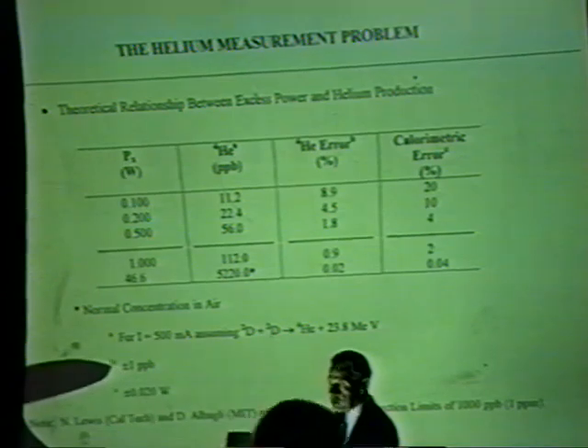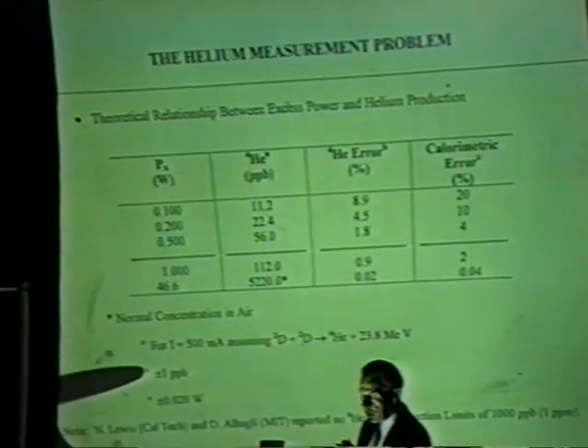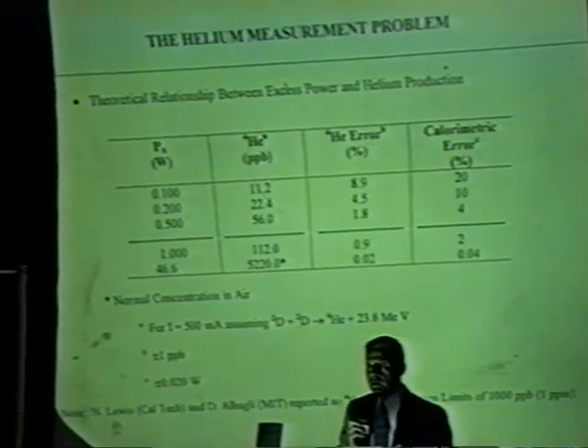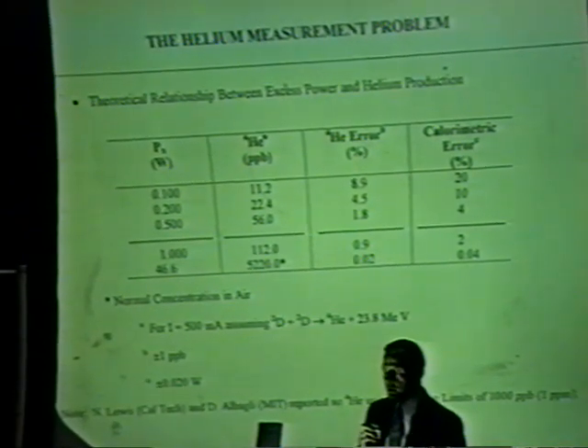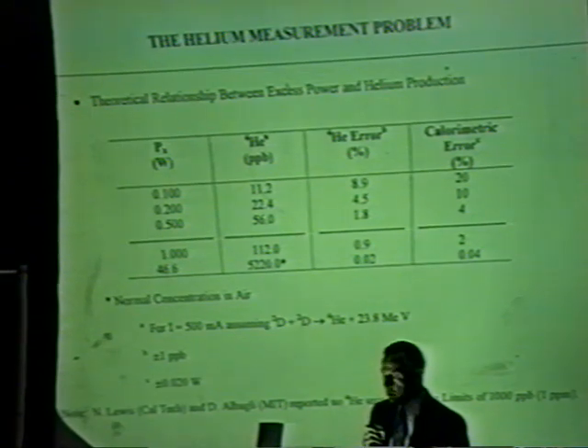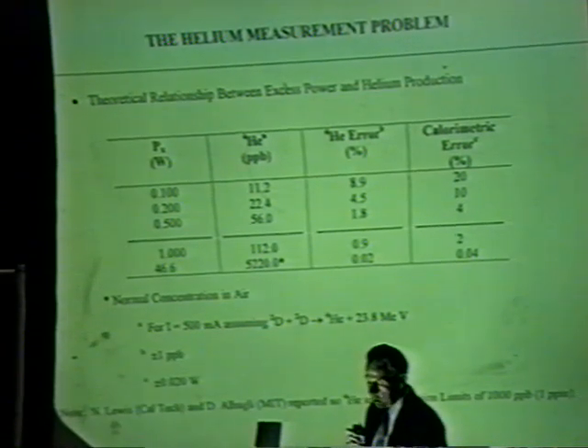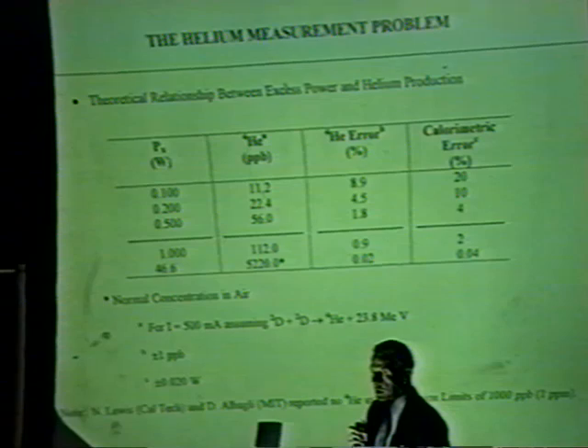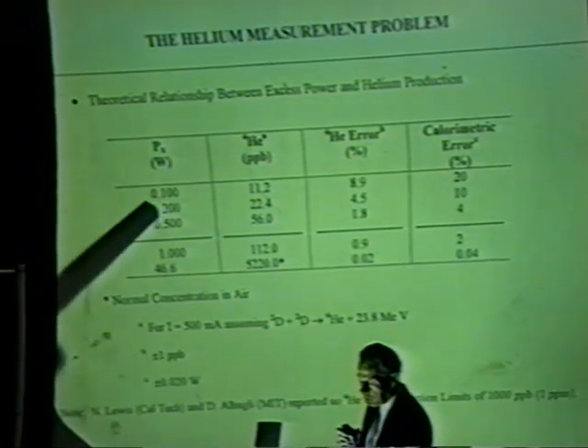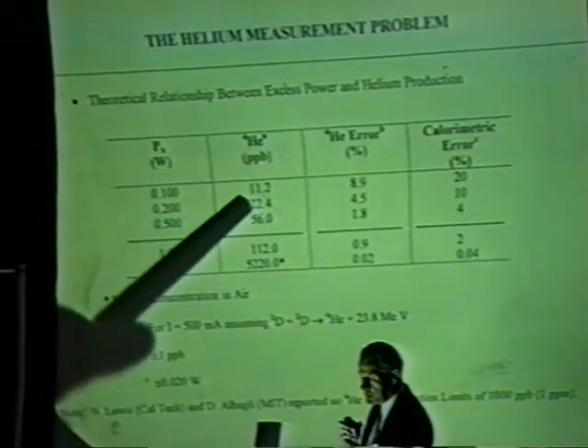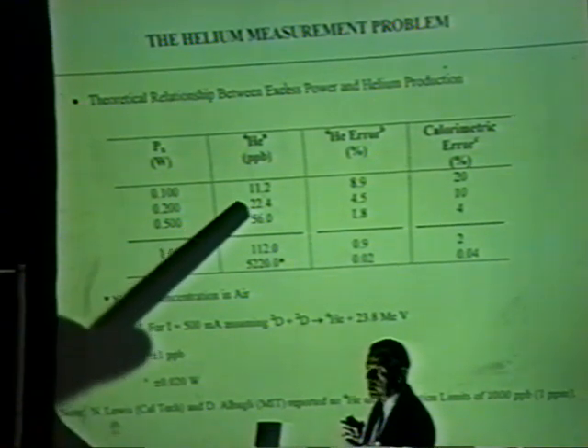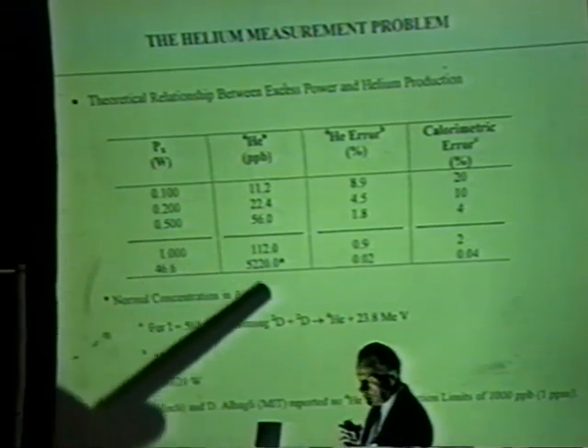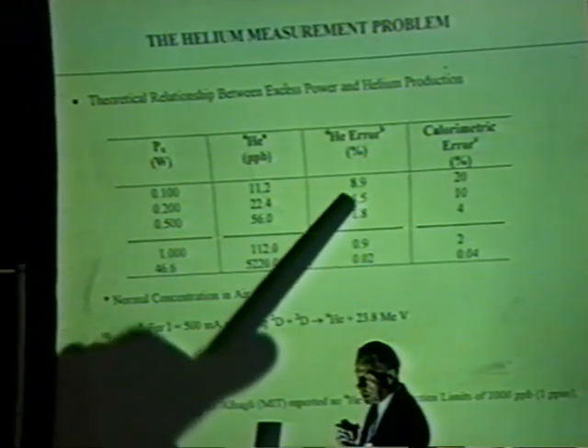This shows the percent error, assuming the error is plus or minus 1 part per billion. That's the error of the Amarillo lab, the Department of Interior lab that we used in Amarillo, Texas. The error was about plus or minus 1 part per billion. And this is the calorimetric error. Assuming for my calorimetry, it's about plus or minus 20 milliwatts. And so for 100 milliwatts of excess power, you would expect about 11.2 parts per billion of excess helium in your sample. And the error on that measure would be about 8.9%. The calorimetric error would be about 20%.